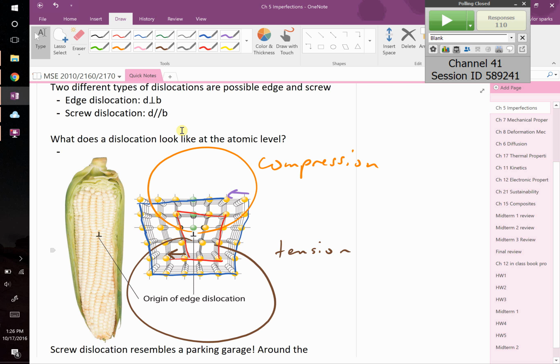Yeah? So would they tend to cause more of an interstitial or a substitutional when they're trying to get in there? Let's just consider substitution for right now. So this is why sterling silver, even though you started out with pure silver and you replace it with something cheaper like copper, is a better material because it's harder, because you put in a copper which is the wrong size. Therefore, I don't know if it's too big or too small. It's probably too small. Therefore, that copper, even though you only add 8 weight%, they sit right here, right?